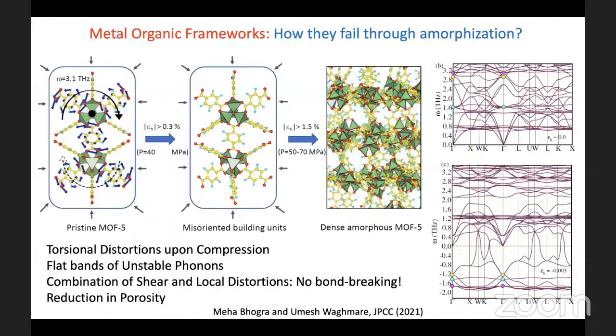You will see that these are the phonons at the bottom, which are unstable. These color circles, blue and magenta, were stable in the reference structure, but they become unstable at very tiny strains. And that led to a structural transition, which subsequently led to a combination of shear strain and local distortion. It involves no bond breaking, all local coordination of various moieties is preserved, and yet you get a huge reduction in porosity and amorphization.